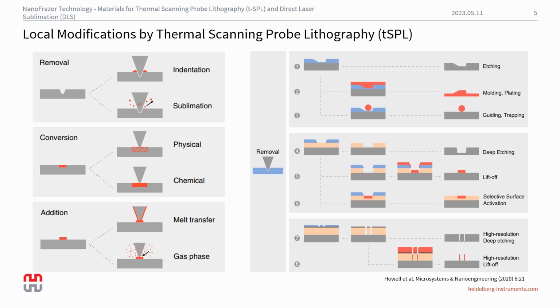So with the removal technique, you have many possibilities. You can go through and perform grayscale lithography, which can be used for molding in imprint lithography applications or even for electroplating complex geometries. You can complement the removal technique with a bilayer process where you can perform liftoff or reactive ion etching to pattern transfer into your substrate. And then finally, we can also perform a high resolution etch and liftoff process through film stack engineering.